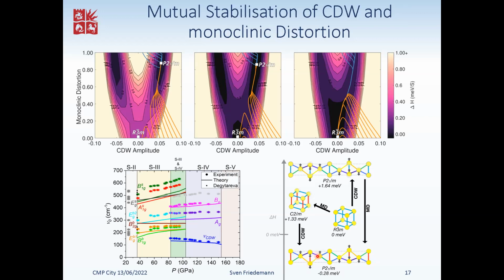And it is exactly this coupling which gives you this abrupt disappearance, because once they become too weak, essentially the coupling gives you a weak first order transition from the charge density wave and monoclinically distorted phase back into the rhombohedral phase at higher pressures. Up here are the energy landscapes that illustrate this. So the x-axis is the displacement of the atoms due to the charge density wave, so the amplitude of the charge density wave, and the y-axis is the monoclinic distortion.